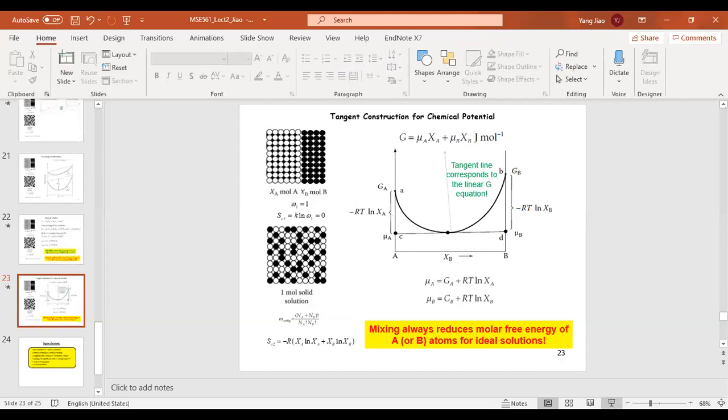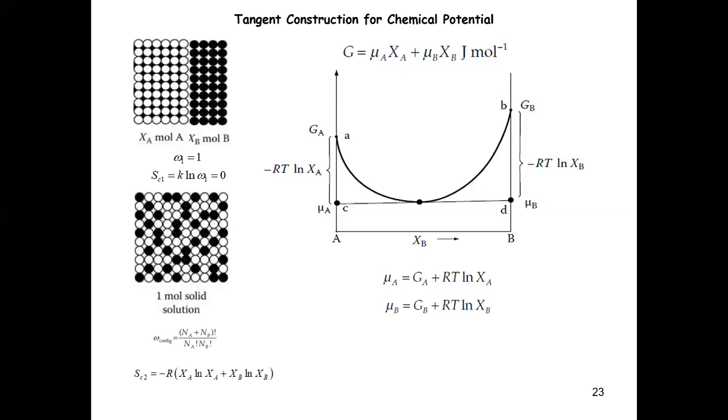So let me go back. Yeah, sure. So does this essentially mean that the molar free energies change if we change the composition? Yes, of course, right? Because as you can see, the molar free energy of the species in the mixing state changes as a logarithm of the molar fraction. So it changes in a nonlinear fashion.